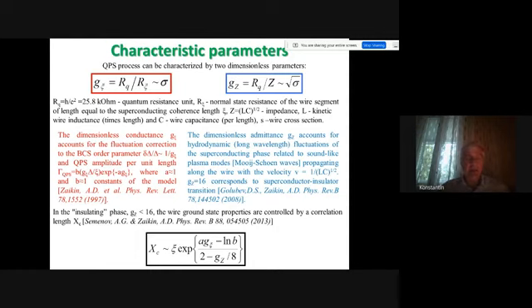But then these events, due to quantum fluctuations, exchange with this plasmonic mode, Mooij-Schön waves. And this is already a collective phenomenon, which is characterized by another dimensionless parameter, which is again the ratio of the same quantum resistance to the impedance of the system. And then our theory showed that the whole story goes along this line. There is a so-called characteristic length scale, which exponentially depends on these parameters. And we call it xi C.